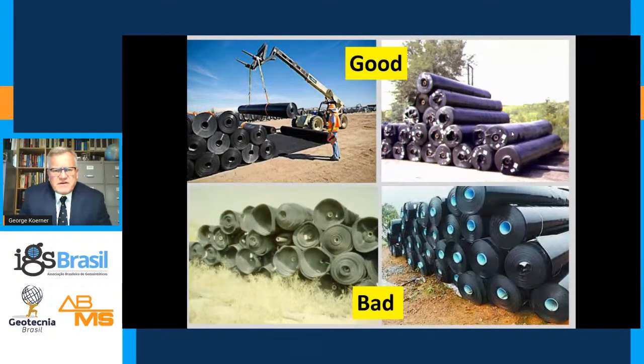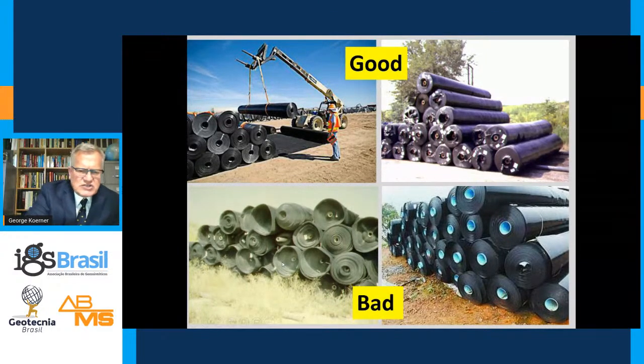In the upper photographs, you see good storage. These are high and dry on a sacrificial piece of geomembrane. The geotextile is covered, it's in wraps, and it's on pipe, which is off the ground. Below is very poor. Here you see weeds growing through a geonet.